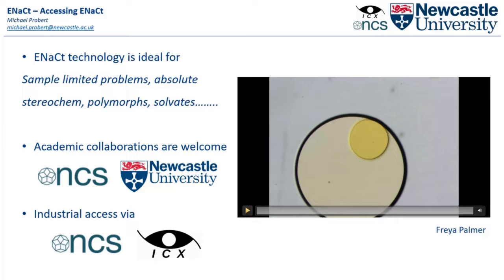I need to just highlight the situation where we have a full understanding, or not quite, of exactly what's going on. So if we watch this little video playing where we have our droplet having moved slightly within the oil to one side, and we're awaiting crystallization here and still awaiting crystallization until we notice that the crystal is actually growing at the oil-air boundary here. So we've had diffusion of our sample through the oil, hit a phase boundary with the oil and the air, has initiated crystallization, and we get crystal growth.